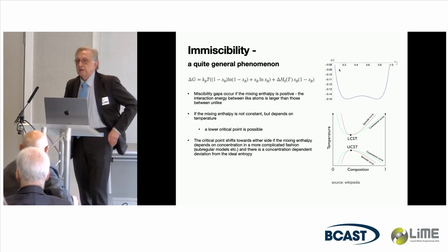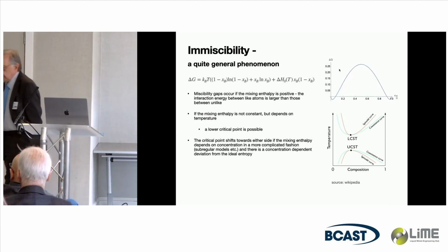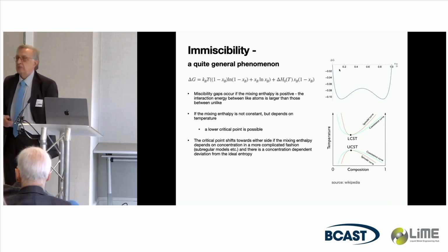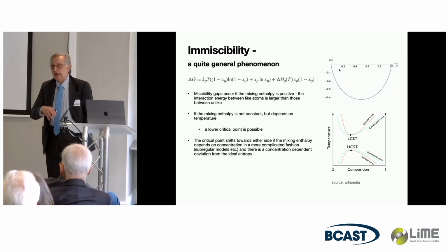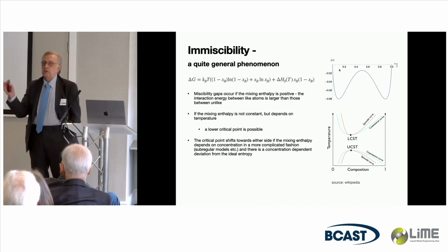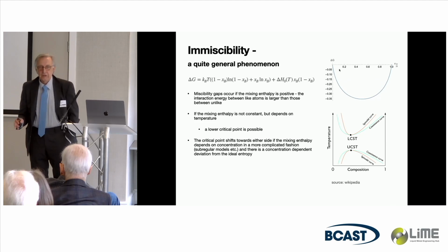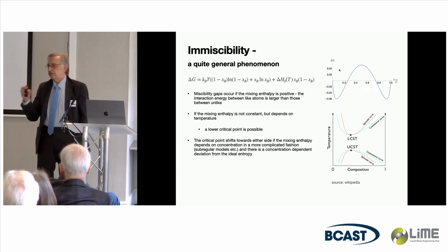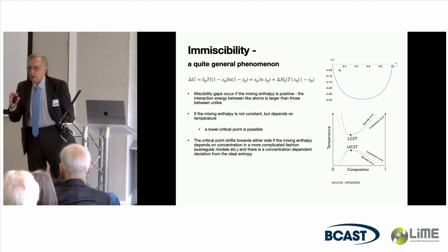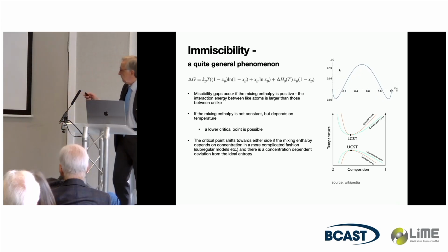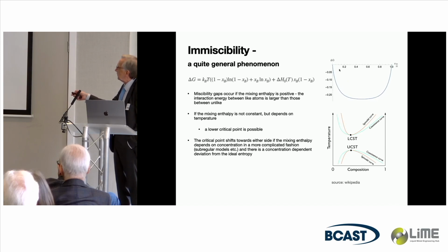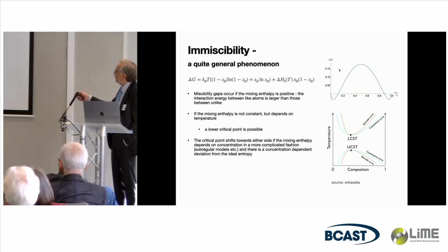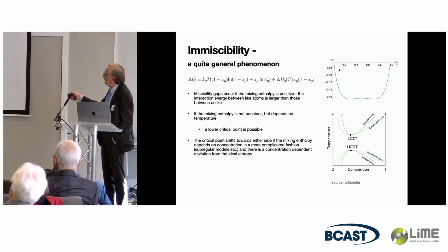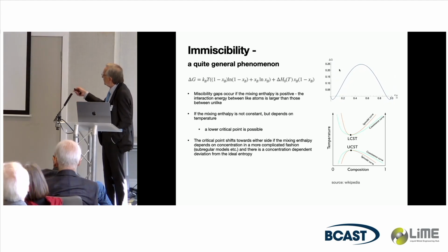Immiscibility is, as you know as a material scientist, a quite general phenomenon. If we would only have alloys or components or elements which are always miscible, what a nightmare. Because immiscibility in the solid state or in the liquid state makes a lot of wonderful microstructures. And it's essentially due, in the most simple model, the regular solution model, to an ideal entropy of solution and of course a mixing enthalpy. The important point is that the mixing enthalpy is positive. Then you see in the free energy diagram that exactly a miscibility gap appears.